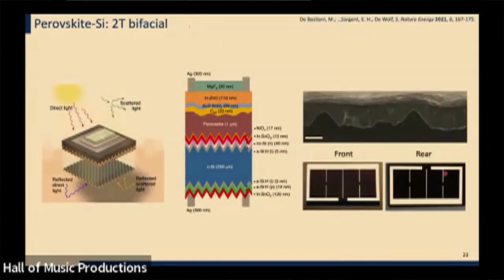One of the areas this is going to now is bifacial solar cells. The legacy approach, the silicon approach, is now not just absorbing the light that's coming in from the top, directly from sunlight, such as what's shown on the left image here, but they're also using reflection and backscattering. It could be off of a specially chosen material, or it even could be off of sand, or it could be off of snow. And they're taking in that light from the backside as well. And when they do this, they can achieve an increase in the overall energy harvesting yield that's accomplished.